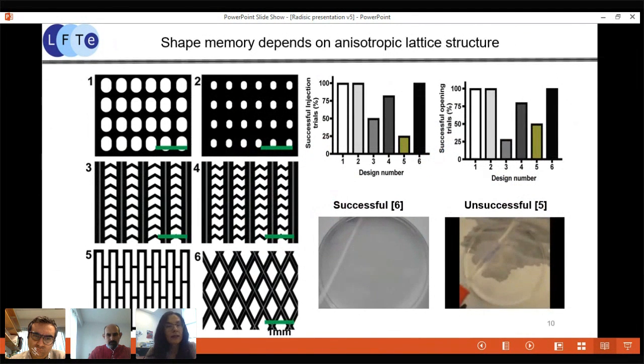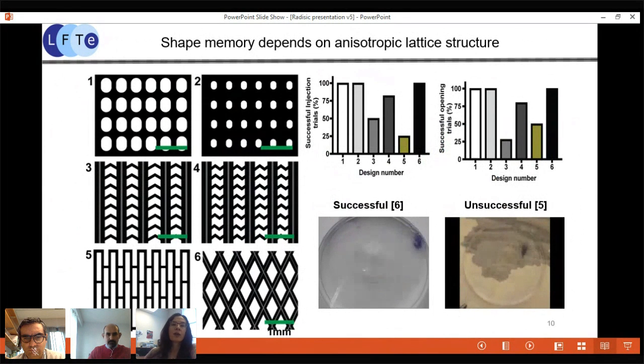The shape memory really depends on anisotropic properties of the lattice structure. So POMAC material by itself has elastomeric properties, and they come from the cross-linking of the linear chains. Basically, a 3D network is created in the polymer, as I showed in a couple of previous slides. And in the clean room, a super talented PhD student from my lab, Miles Montgomery, who has since graduated, designed PDMS molds that enabled us, through capillary action, to perfuse these molds with POMAC polymer and cross-link it with UV illumination.